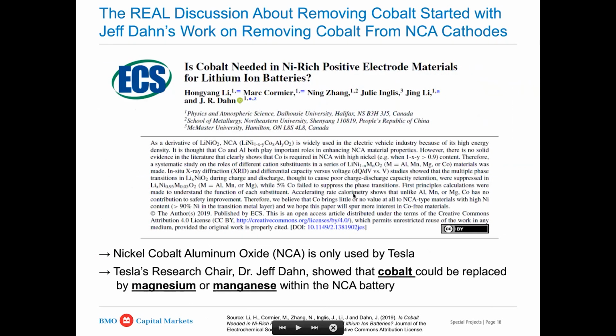We've been talking about NMC 811, and why cobalt's needed in the system, for a very long time. But the real discussion around removing cobalt started with Jeff Dahn's work on removing cobalt from NCA cathodes. This was actually the star that I thought was the big thing that was supposed to be at Battery Day, but Elon Musk just basically said it real quick and then moved on. They were able to switch, within the NCA, cobalt with manganese or magnesium. But I think that's going to be an NMA. What they're going to be working on is basically a nickel, magnesium, and aluminum cathode, but we'll see what happens.